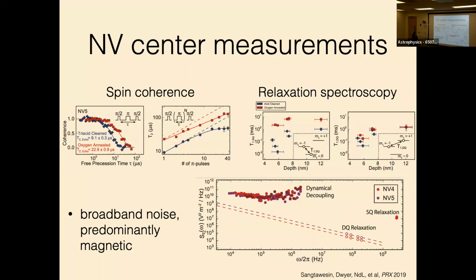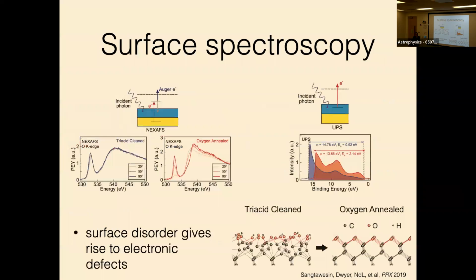And we can work hard to try to put all of these things together on one footing to create one nicely parametrized plot where we look at the electric field noise with its 1/f scaling compared to the magnetic field noise, and we see that the magnetic field noise is really dominant by about 2 orders of magnitude. Okay, so those are the NV measurements, and then we can also do this surface spectroscopy to see what changed in the surface spectroscopy.